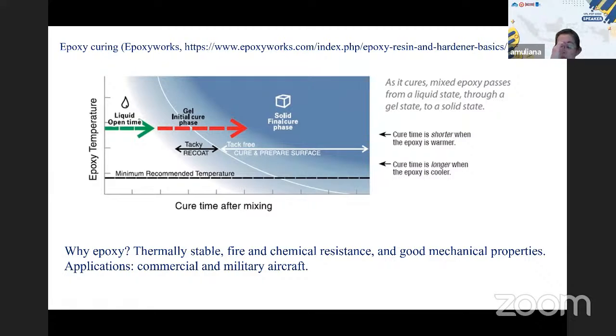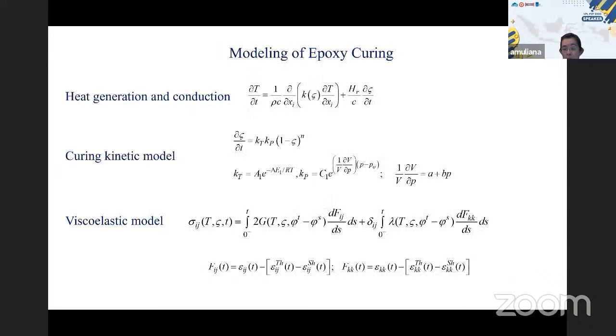All of this would affect the curing process in the polymer, where it can also generate thermal stress, where if we have excessive thermal stress, it might induce defects. These are what they call processing defects, which is something that we want to control or mitigate. Now, how to do this? Of course, we need to understand the entire processing factor and history of this polymer. Now, without going into detail, the essential mechanics are heat generation and conduction, because it involves high temperature. So we do have it at a relatively high temperature. There is conduction, and during this curing process, the heat is being generated.